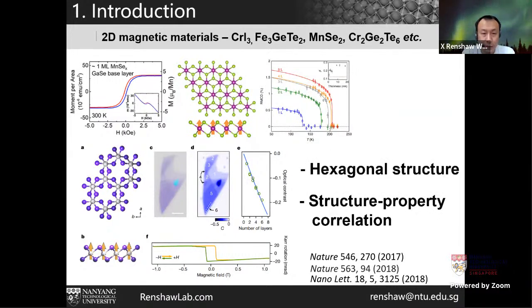But also, if you look at the structures, most of these 2D materials or 2D magnetic materials have a hexagonal structure, so there's a clear indication of a structural property. A very interesting correlation, not really correlation, relationship, because it looks like most of the 2D materials, if they are hexagonal, then they can possibly be magnetic.